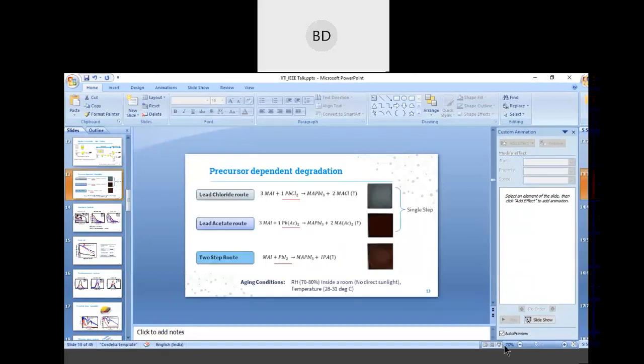Aging factor determines which parameter? Sir, the aging factor will determine the formation of colloids in the solutions. Like we have done in some other experiments, which I have not reported here. In the last of my slides, I used lead nitrate as the precursor composition change parameter. So if you use PbI2 and lead nitrate and keep the solution for aging, then there will be colloid formation in the solution itself, and that colloid formation will further improve the perovskite morphology. So if you keep the solution for aging, it can improve the performance further. So this is how the aging parameter can help the perovskite morphology.